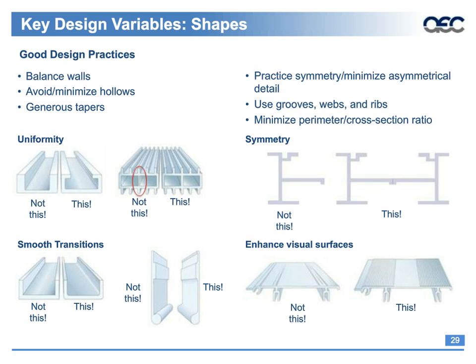Each one of these examples shows this, but not this. But in fact, you can do either one of them. So starting in the upper left, that thin-walled bottom C with the thick walls on the left and right can be extruded. But if you don't need those thick walls right and left, if you just need more of a C shape for perhaps spacing reasons or whatever, the shape on the right will extrude better.